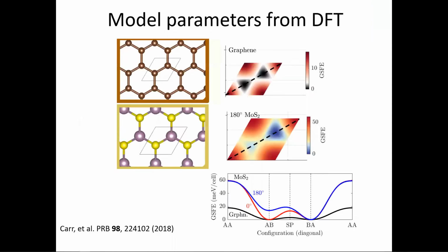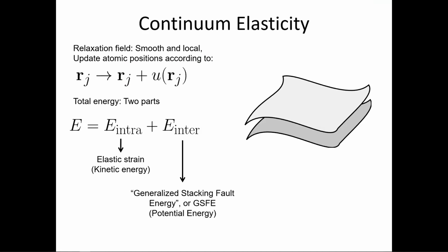I have a question. Sorry, I asked too much, but basically, in this case, you consider the elasticity of the lattice. So R here is the lattice position, not the electron, right? Yeah, this is a purely mechanical problem. This is a continuum plate theory. Now the electrons play a role in affecting the strain coefficient, but you basically extract some sort of bulk and shear moduli from a DFT calculation or from an experiment, and then you don't worry about the electrons at all.